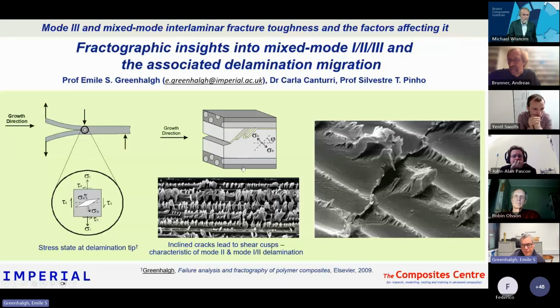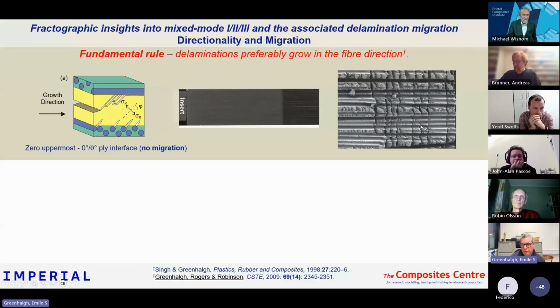So in the 0-0, you get these shear cusps. If you move to a 0-90, you can see the shear cusps, but you also start to get these secondary gouges, is what we call them. They're associated with secondary cracks that initiate at the 90 ply below and extend and emerge at the delamination plane. So this is an added fracture mechanism, adding to the toughness. I found, under mixed mode conditions, about 40% improvement in the fracture toughness in the 0-90 as compared to the 0-0 for the same material system.